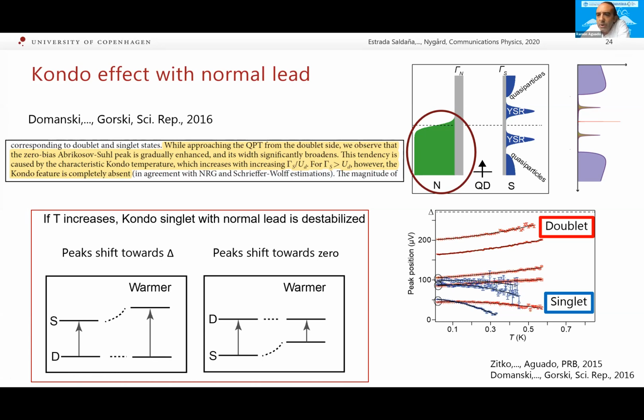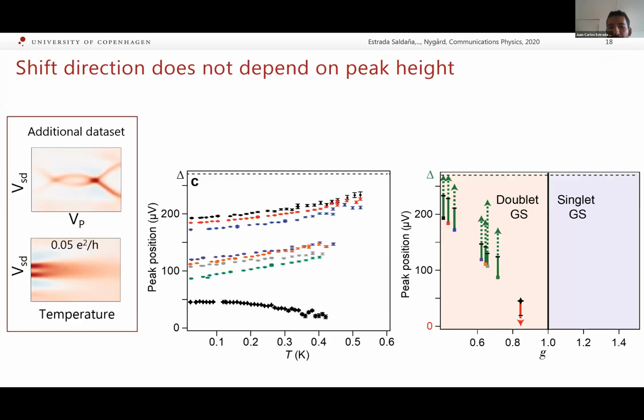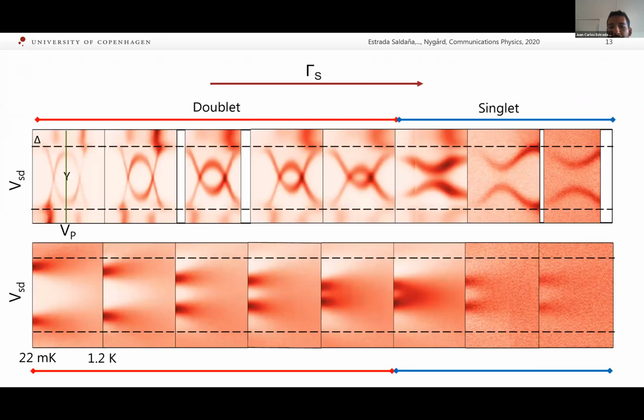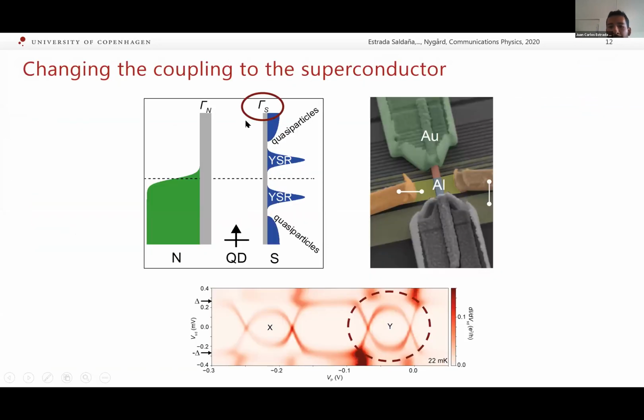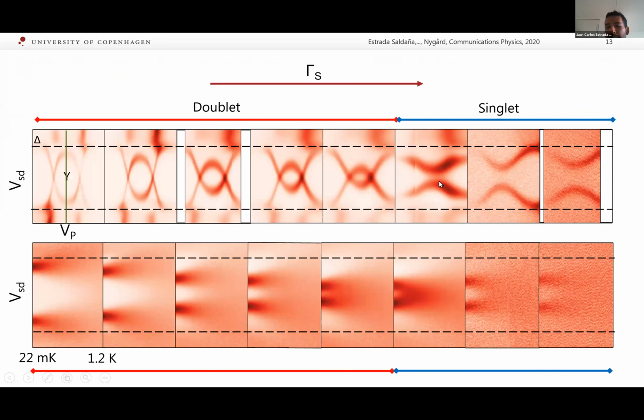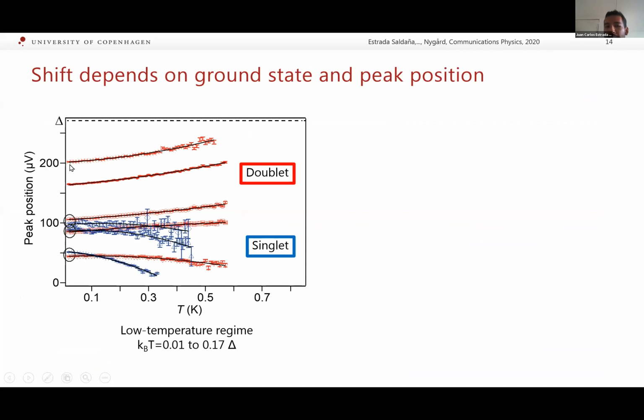So I wanted to ask you, maybe you mentioned and I missed it. Do you have how this temperature dependence changes as you change the coupling to the superconductor? Have you done this kind of measurements? Maybe you mentioned it and I missed it. This is these measurements right here. So here we're changing the coupling to a superconductor. Yes. And this is what we see. And this is that there is a difference when we are approaching the doublet to singlet side. And we extract this from a fit in the peak position.